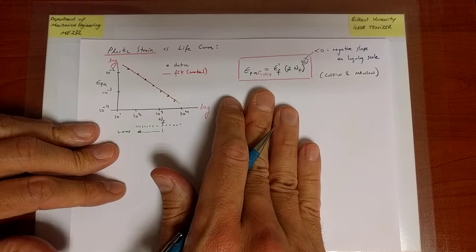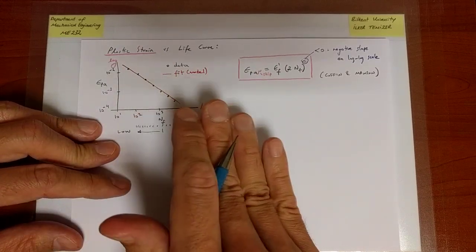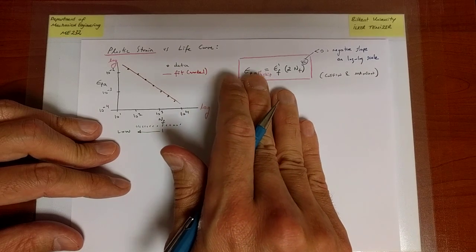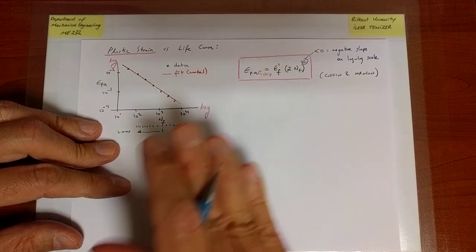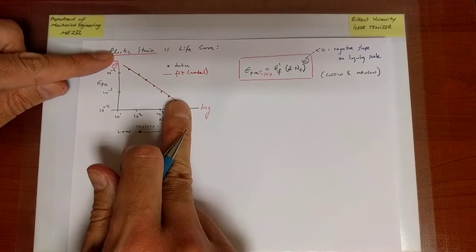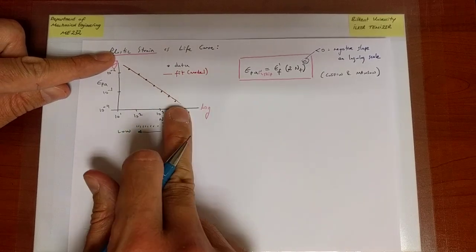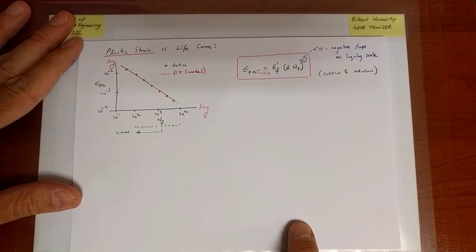Low cycle fatigue is where significant plasticity occurs, and so the idea is that, well, why don't we monitor the plastic strains? Of course, I'm referring to the alternating portions only, and map it to number of cycles to failure. That's a very clever approach, and it turns out that's an approach that is very amenable to modeling because the data is rather supportive of such a model.